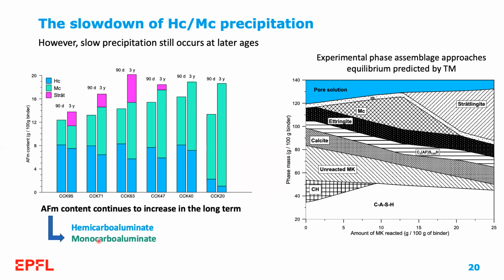Particularly, in addition to hemi and monocarboaluminate, we also observe stratlingite, which is the third type of AFM phase. And in this case, we can also observe that the experimental phase assemblage in the long term starts to approach what we can compute by thermodynamic modeling. In two ways: we observe stratlingite in our high-grade systems with metakaolin contents above 47%, and also because the proportion of hemi and monocarboaluminate shifts towards monocarboaluminate, which is also something that is predicted by thermodynamic modeling.